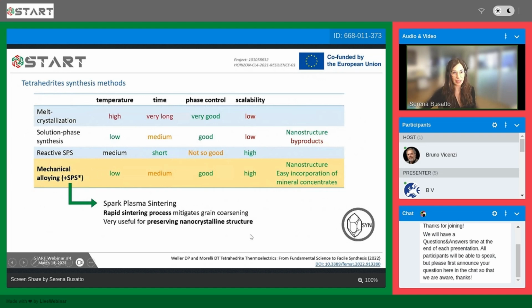And finally, mechanical alloying followed by spark plasma sintering is one of the best methods for the synthesis of tetrahedrites because of the low temperature, medium time, good phase control, high scalability, and also nanostructuring and easy incorporation of the mineral concentrate. And then the spark plasma sintering process mitigates grain coarsening. That's very useful for preserving the nanocrystalline structure.